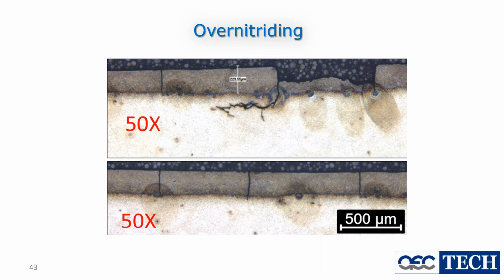And then the crack you can see is the same as the thickness of the nitride layer. So if the crack is bigger than the critical crack size for that material, the crack can grow and then go through the whole tool and break the tool. So this is also one of the problems with overnitriding. Another reason for the failure is that there's a narrow transition zone compared to the thickness of the nitride layer. So getting everything controlled and keeping it within limits is very important.